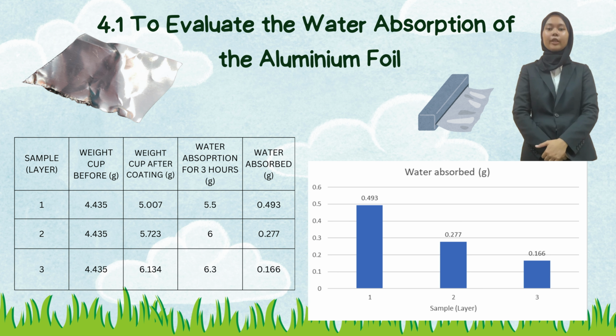From the results show, we can see that the water absorption of the aluminium foil coating decreases as the number of layers increases. Sample 1 with 1 layer absorbed the highest amount of water, 0.493 gram. Sample 2 absorbed less water, 0.277 gram, while sample 3 with 3 layers absorbed the least, 0.166 gram. This indicates that adding more layers of aluminium foil enhances the water resistance of the coated cup. The extra layer acts as an additional barrier preventing water from penetrating the material effectively. Therefore, multi-layer aluminium foil coating provides better protection against water absorption.